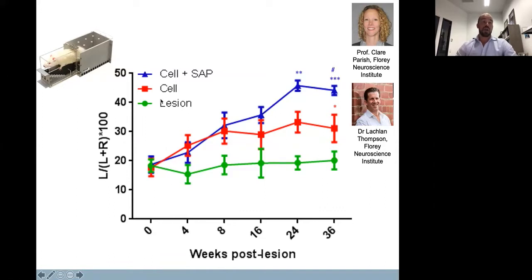And what you can see with the red here, when we put the stem cell graft in, is that after 9 months, we do see a significant improvement in coordinated paw function with the stem cell graft. But more striking, even after 24 weeks when we have the material present, because we're presenting that IKVAV epitope and we're using a material as a delivery system to protect the cells during administration, we're getting these larger grafts and we're presenting relevant biological motifs to encourage their survival and integration, and we're getting much better functional recovery even then with the stem cell graft when we have the materials and the stem cells.